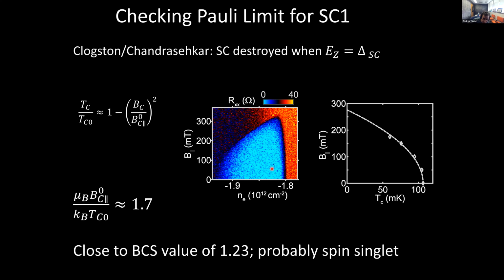And if you do this measurement, so now you can look at the in-plane magnetic field dependence of superconductivity, plotted here as a function of density. Just as before, you see that it survives up to several hundred millitesla. But that's actually rather consistent with the transition temperatures that are observed. So you can see that it's a pretty good fit to this BCS formula. The value is something like 1.7, whereas in absolutely vanilla BCS, it's supposed to be 1.23. But a survey of the literature suggests most superconductors don't nail this right on the head. This is not a very big deviation, and so we can basically conclude that probably the spin structure of this superconductor is spin singlet.